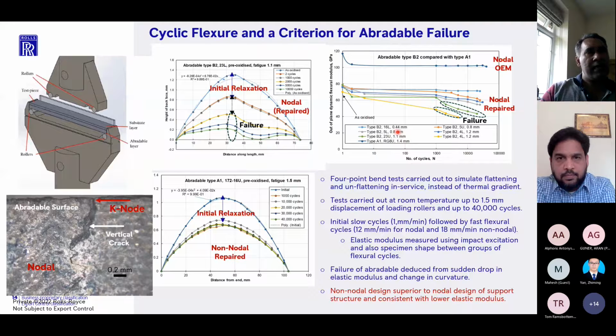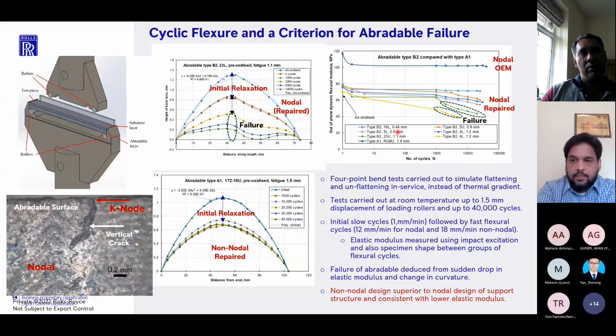What we did was look at some 4-point bend tests. If you remember, like I said, in service you have thermomechanical fatigue, you've got a temperature gradient across the hook to the hot gas wash surface. Because of this temperature gradient, the material flattens and unflattens in service.